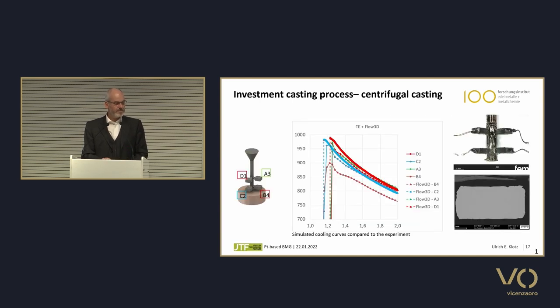We did the same. This is the measurement of the temperatures. We had the simulation; the dotted lines are the simulations, and the solid, thicker lines are the measurements. And we see that there is quite good agreement between the calculation and the measurement. You see the thermocouples after the casting sticking to the parts, and we obtained a defect-free casting.